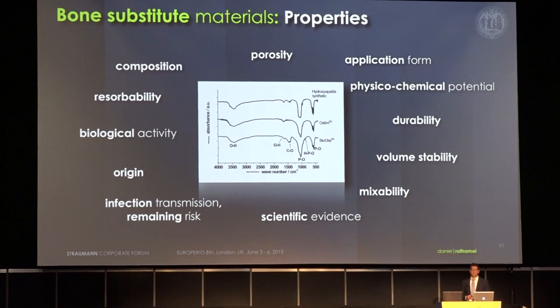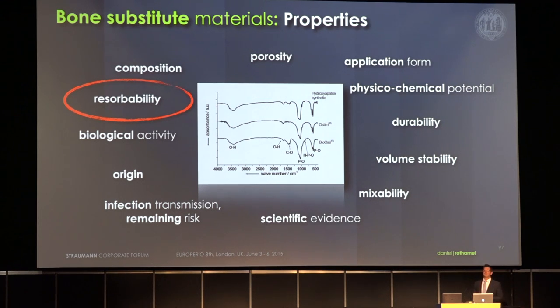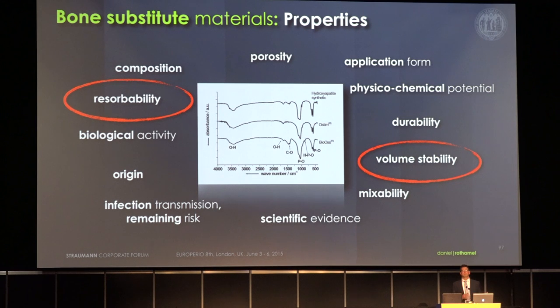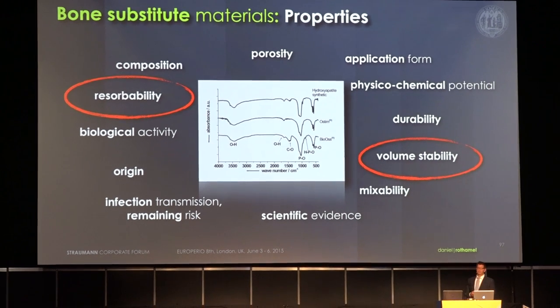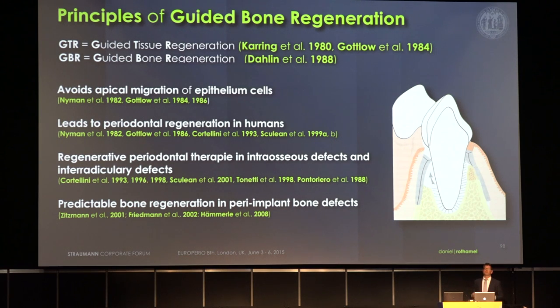In the past, the focus was that a perfect bone substitute material should be resorbed very quickly, being completely replaced by the patient's own bone tissue. However, we now have studies showing that after 10, 12, or 15 years, bovine bone substitute material embedded in the patient's own bone shows no resorbability — but this actually supports the volume stability of the graft. When we have a material that shows very slow resorption or just superficial remodeling, this is a very good aspect for maintaining long-term volume stability. Without membranes, soft tissue invades the defect, leading to soft tissue encapsulated bone substitute material areas.